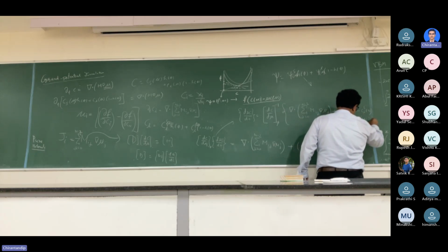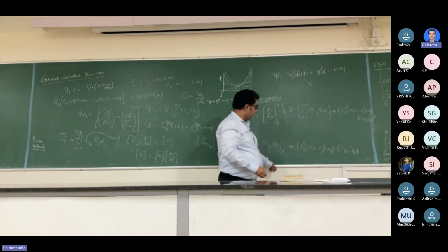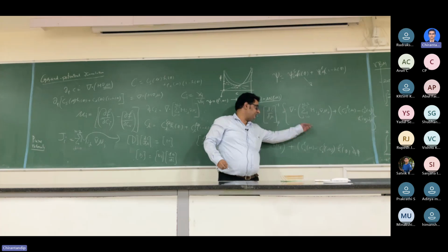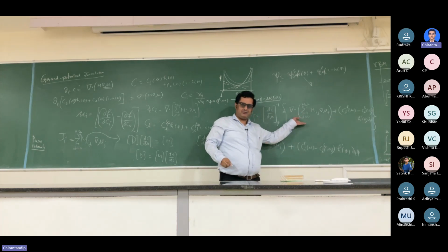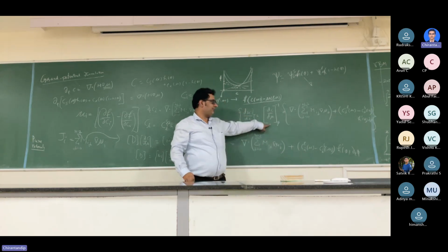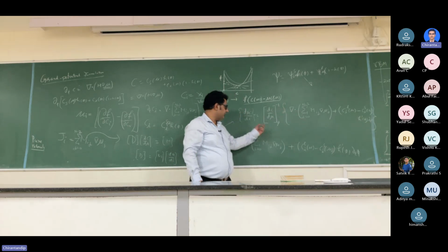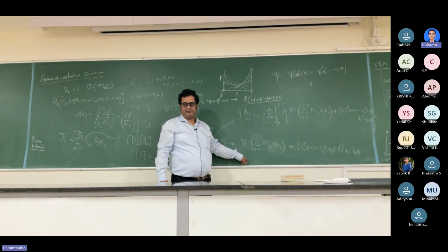This is a vector containing all the components. Each line is for the ith component, and we have n minus 1 here. This is a matrix which is n minus 1 cross n minus 1. The matrix inverse times this gives you the d mu i by dt, all at the same time.